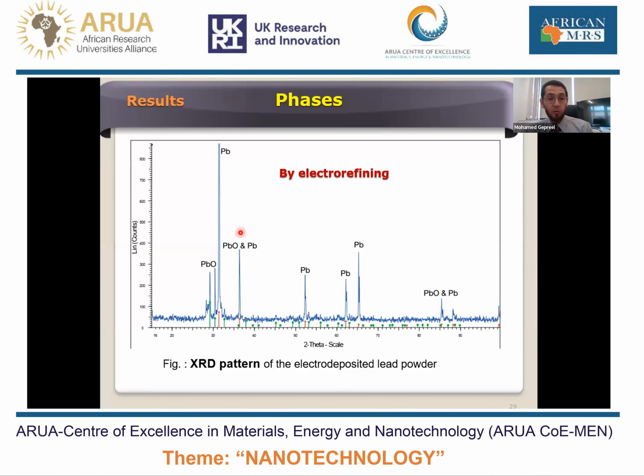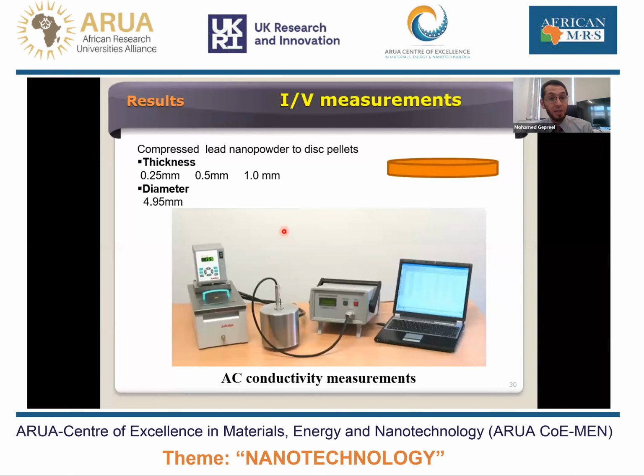Once we have such a lead oxide mixture and core shell, the idea came to me: why don't we use it? Because lead oxide has semiconductor characteristics. Why don't we use it for some physical property measurements like radiation sensing? So we make discs of this type of powder in different sizes to consider the size effect of the disc, and measure the electrical conductivity as a function of the given conditions.